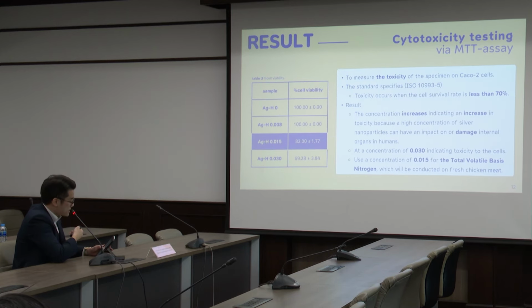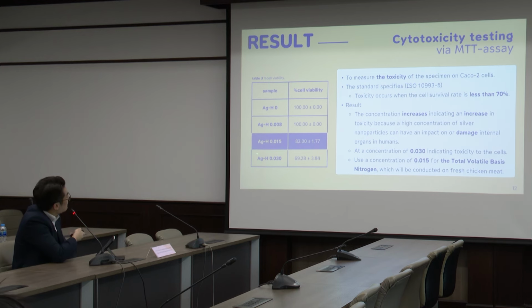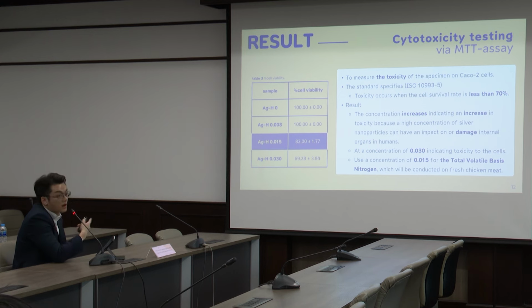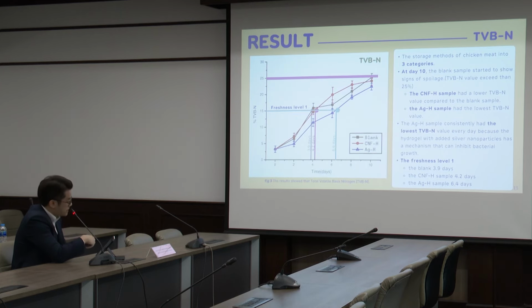So the cytotoxicity test we conducted measures the toxicity. As I said, we use the Caco-2 cell line, which represents the intestinal epithelial cell. The standard specifies that toxicity occurs when the cell survival rate is less than 70%. If you see in this table, the increasing silver nanoparticles provide a decrease in the percent cell viability, and at the high concentration, the cell viability is less than 70%, which means it's already toxic. So we have chosen the concentration of about 0.015 phr for the TVBN test, which will be conducted on fresh meat.